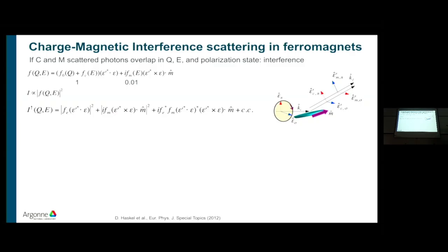Circular light is nothing else than two orthogonal polarization states that are out of phase by 90 degrees, right? So the light rotates clockwise or anti-clockwise for the other helicity. So charge scattering doesn't rotate the polarization, so you go blue, blue, red, red. And the magnetic scattering rotates the polarization, so blue goes from horizontal to vertical, and red goes from vertical to horizontal, but it's still circular or elliptical. So these two photons actually have polarization states that overlap. And then when I compute this scattering amplitude, now I have to worry about this interference term, because there is interference between the charge and magnetic scattering channels.